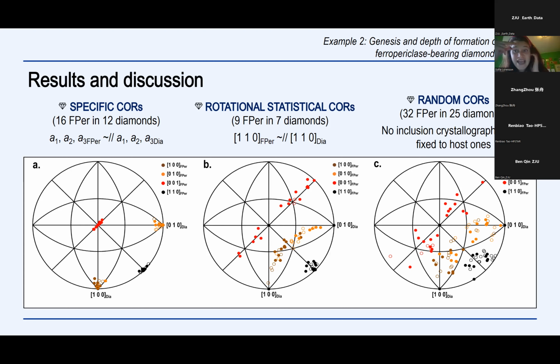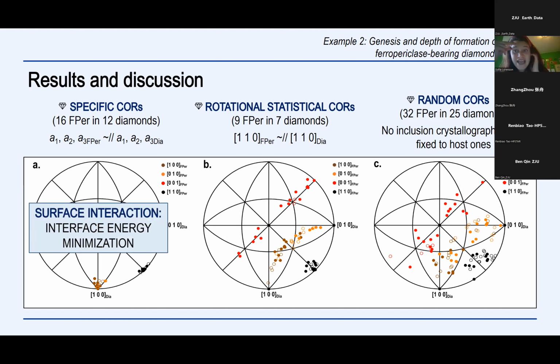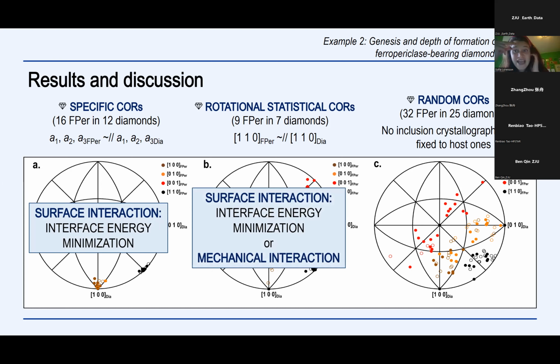But what does this mean in terms of genetic processes? The development of different orientations can suggest that probably ferropericlases and diamonds interacted in different ways when the ferropericlase bearing diamonds formed. Specific orientations can suggest, for example, that during the formation of the ferropericlase diamond system, the two minerals interact through a surface interaction in order to minimize their interface energy. On the other hand, the presence of rotational statistical orientations can suggest, as in this case, a surface interaction, but can also suggest a possible mechanical interaction. But in our case, we exclude this possibility because for having this kind of interaction, we must have very well-developed crystals.